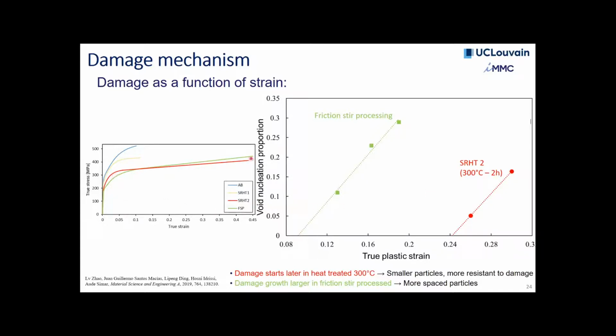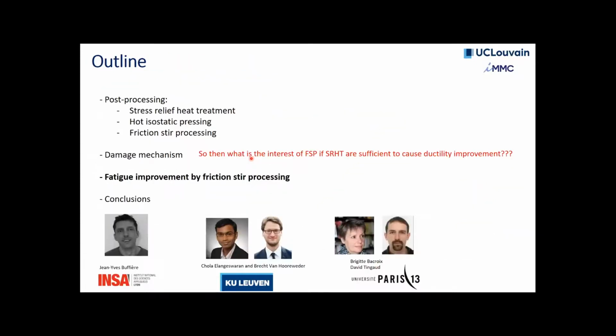So basically, we're ending up with a stress relief heat treatment that is very similar to friction stir processing in terms of static properties. So you would tend to say that probably it was not so interesting to do friction stir processing; stress relief heat treatment was more interesting in that perspective. They have the same utility. But then we went into looking at fatigue, and you hear all names of people that have helped us. This was the work on hot isostatic pressing that I've shown you already, just to show you that we're not really convinced about the solutions that we found for hot isostatic pressing.